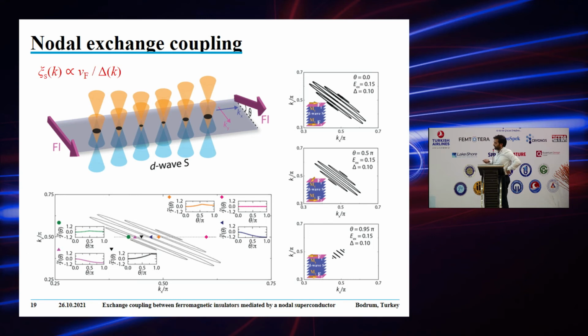Now, each of these channels in the Brillouin zone, if you calculate the free energy of each of these channels, you will see a different evolution as a function of theta, where theta is the angle between the two magnetizations, depending on whether it's inside or outside the Fermi pocket. So basically, when you change the orientation of these two ferromagnets, each channel contributes differently, and if you integrate over the entire Brillouin zone, you can determine the minimum of the system.